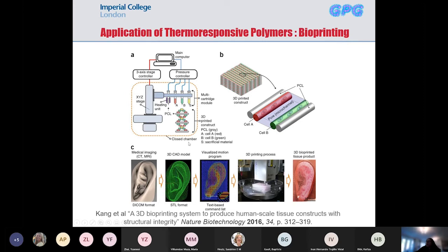So actually the polymer here that they used that is a thermogel was Pluronic F127. That is where they say that we have the sacrificial material. So essentially they use the Pluronic thermogel. They stabilize their system within that gel. They printed it at elevated temperature, and then they let the material cool down, and then the Pluronic became a liquid again, and then it kind of left the scaffold. And what they wanted was not for the polymer to be incorporated within the scaffold. So in this case, the thermoresponsive polymer is the sacrificial material, in the sense that it was sacrificed and removed at the end.